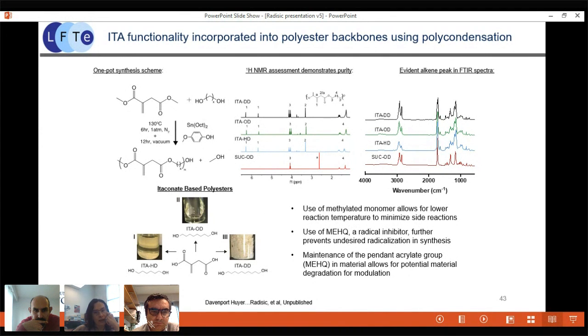And you can see here that if you control the alcohol chain length, you can create materials of different appearance. So you can have a liquid, you can have solid, or you can even have gel appearance. But it's still a liquid, it just appears as a gel. And so Locke was able to demonstrate successful incorporation of both itaconate and these specific alcohols into the polymer.